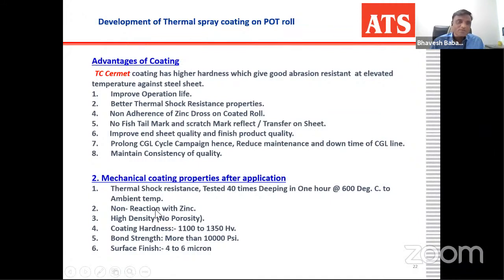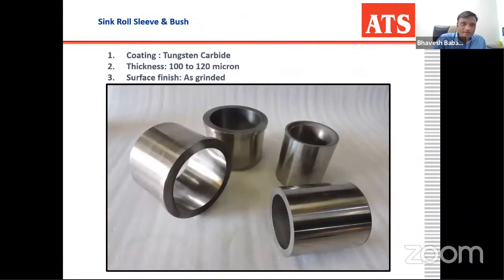Coating hardness is 1100 to 1350 HV, which is good hardness, and bond strength is more than 10,000 psi, so it does not easily peel off from the roll surface. After the coating, we generally get a surface roughness of 4 to 6 micron. It's very good for our sink roll. Also, we supply the sink roll sleeve and bush with the special coating.